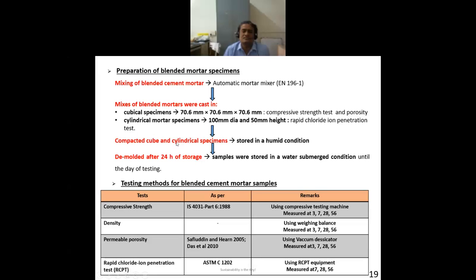After the casting, they were stored in humid condition and demolded after 24 hours of storage. Once you demold after 24 hours, you keep it for proper curing until the day of testing. Here we have adopted submerged water curing. Then the testing methods for blended cement mortar samples are compressive strength, density, permeable porosity, and RCPT. As per standards, there are codes we have adopted or some references. Compressive strength was done at 3, 7, 28, 56 days. Same for density and permeable porosity. RCPT was done at 7, 28, and 56 days.